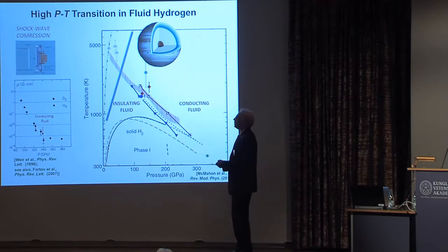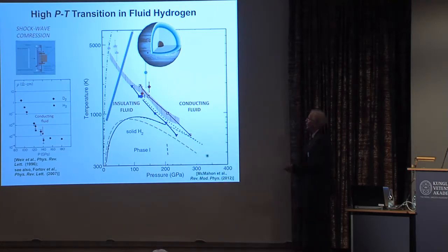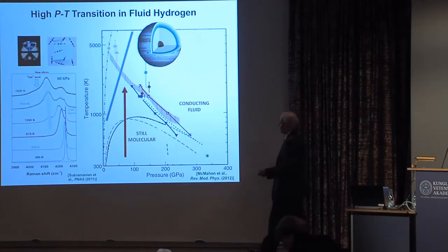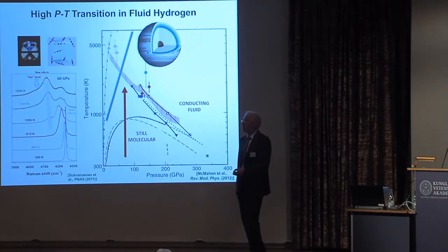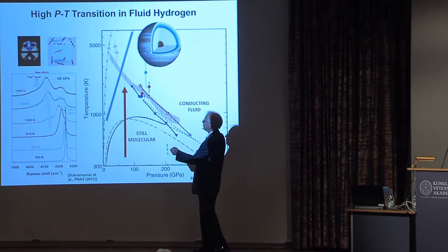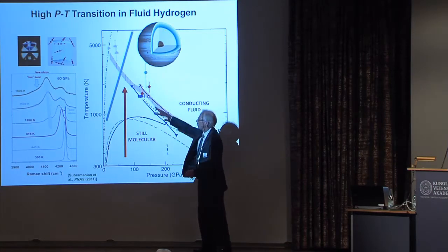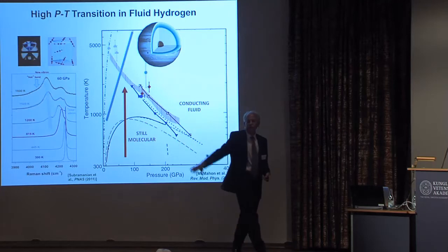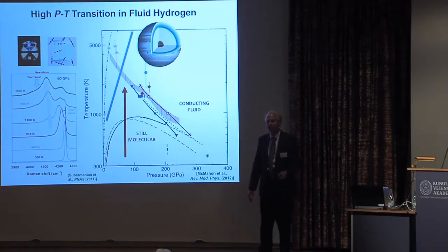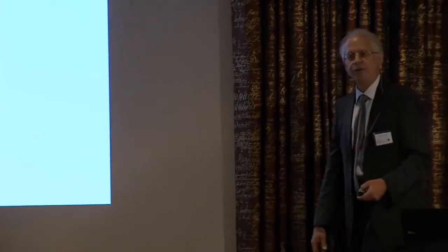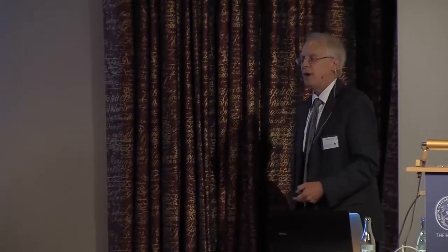This is interesting from the standpoint of the behavior of hydrogen inside planets because this is the PT path that one follows in the case of the interior of Jupiter, and so it crosses here. So this suggests there could be a transition to a conducting fluid over this range. Well, what can we say about the state of hydrogen in this range of pressures and temperatures? Well, we've done high temperature measurements now, studying this vibron of the intramolecular stretching mode, and we see that the molecules are stable over this very wide range, so it seems to be molecular in this dense fluid, and we need to now move off into this region to look at the conducting fluid. But clearly there's a need for higher pressure measurements, at higher temperature measurements.